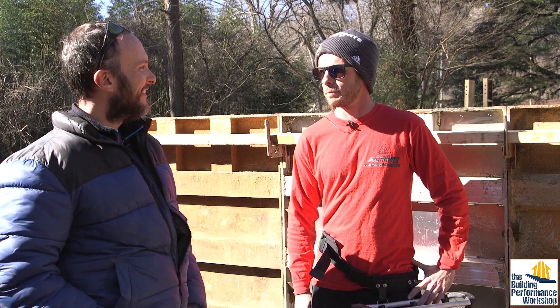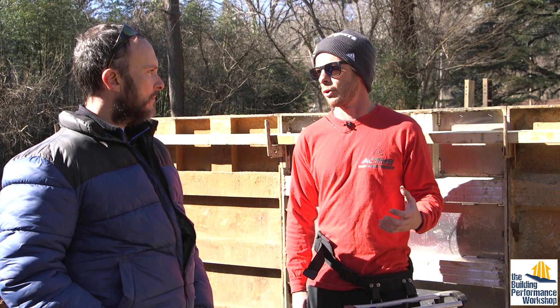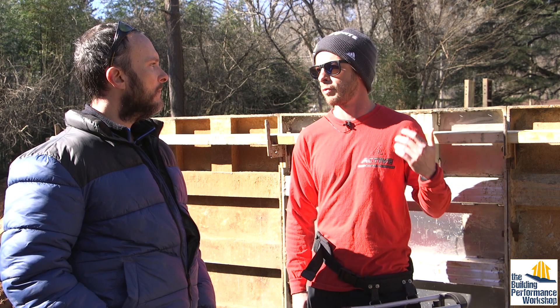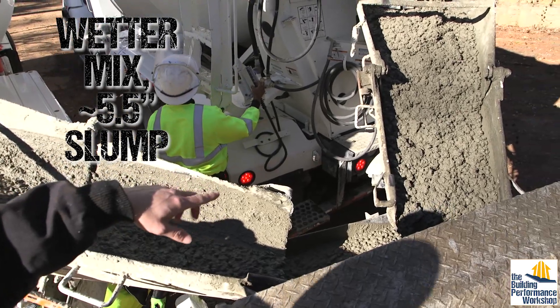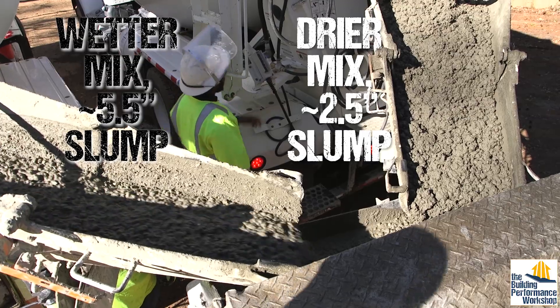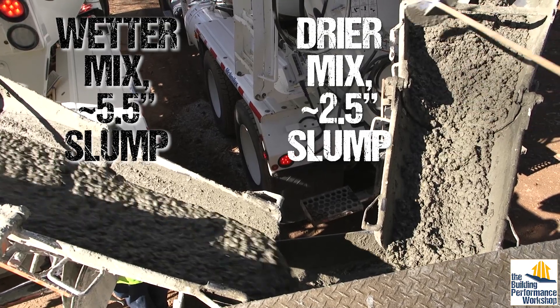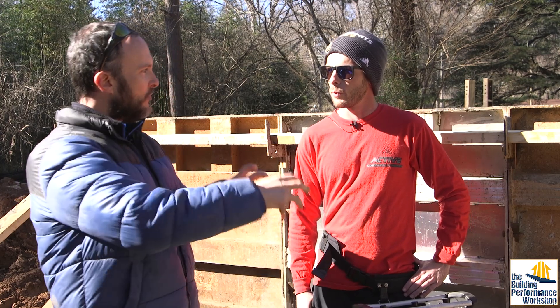Everybody does it a little bit different. A lot of times, if we're doing a footing, we want to have a tighter slump — maybe a three and a half, four, four and a half, somewhere around there. Some guys like five. It just depends. You want to talk to your finishers and see what they want to do as well. So that's why we like a little bit wetter slump — five, five and a half. If you come with a three-inch slump, most of the time no, unless it's a commercial job where they have to have it at a certain slump. When the concrete leaves the plant, they're going to have it at a certain slump, but then if a guy gets stuck in traffic, he's going to maybe add more water to it to make sure it doesn't dry out.